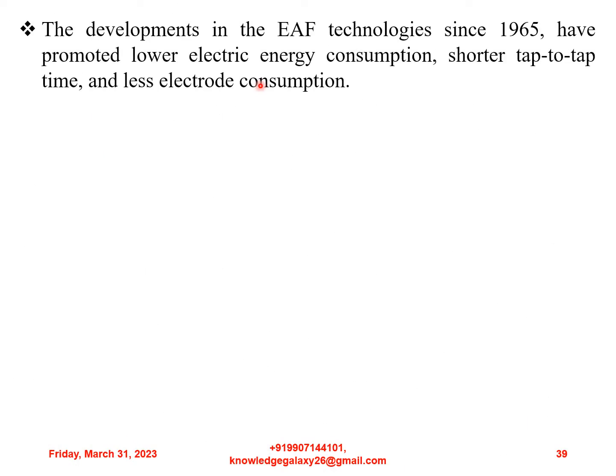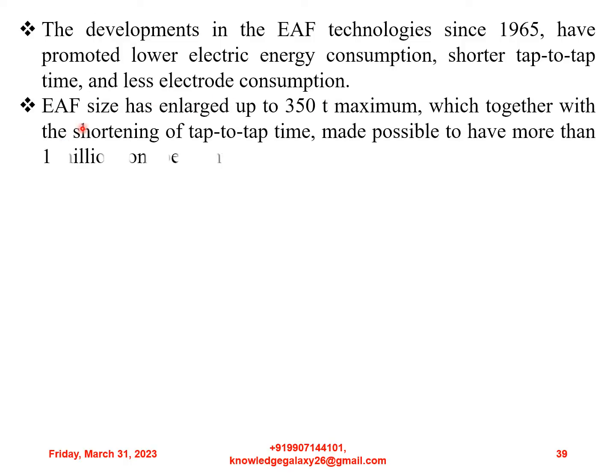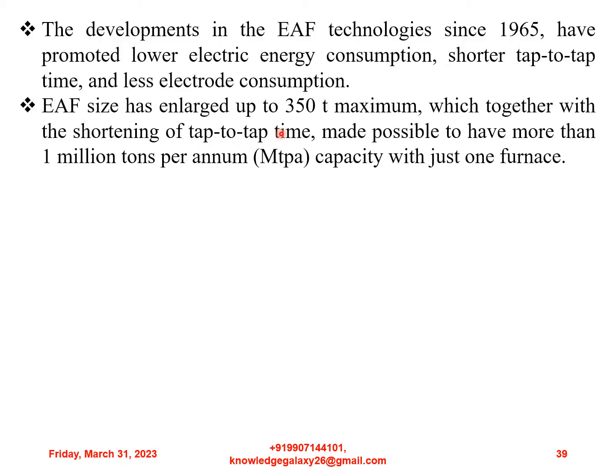The developments in electric arc furnace technologies since 1965 have promoted lower electric energy consumption, shorter tap-to-tap time, and less electrode consumption. Electric arc furnace size has enlarged up to 350 ton maximum, which together with the shortening of tap-to-tap time made it possible to have more than 1 million tons per annum capacity with just one furnace.